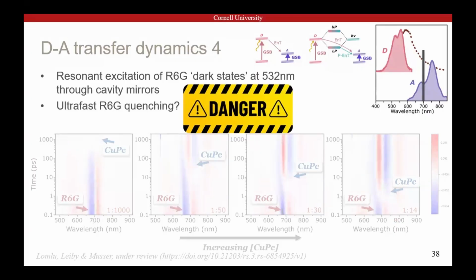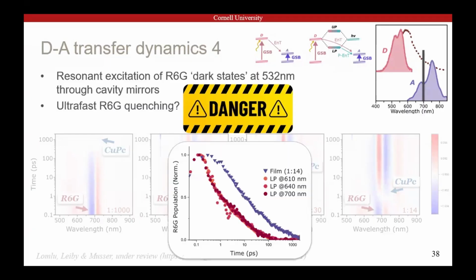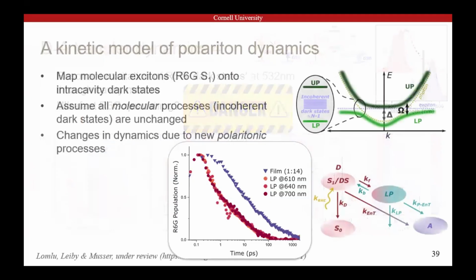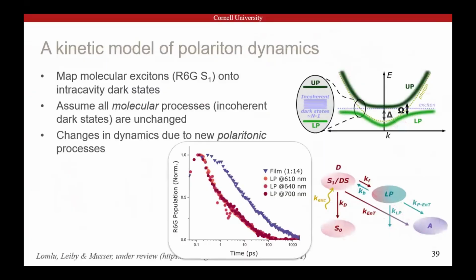You have to be incredibly careful in how you decompose it. It took us a long time to work out the right robust method. When we did, we found there are very, very tiny differences at most between the different cavities, but a massive difference between polaritons and the film system. And that was enough to build a simple kinetic model. I'm just going to go over the key points.